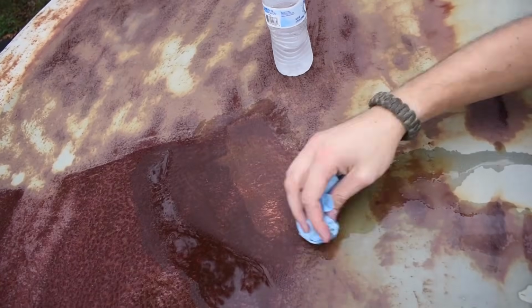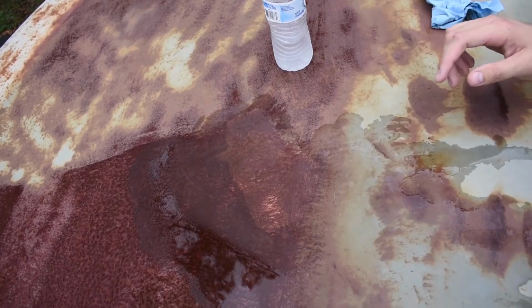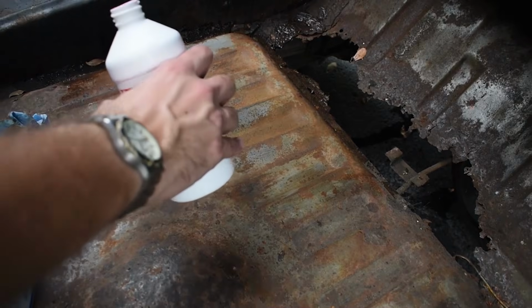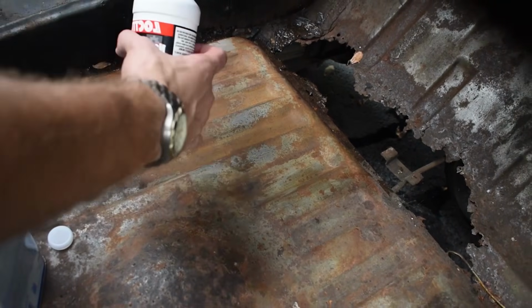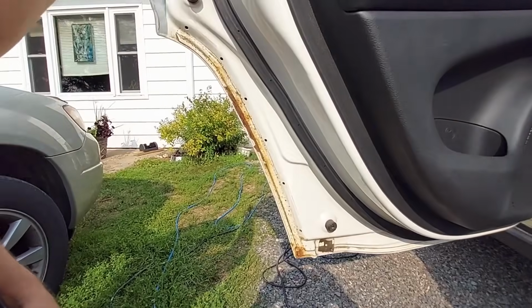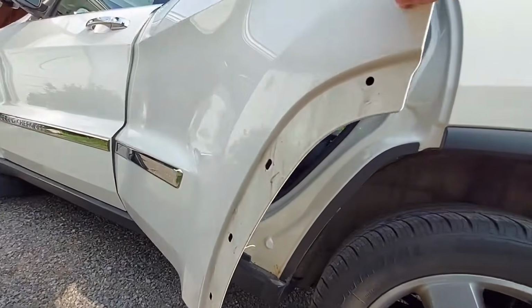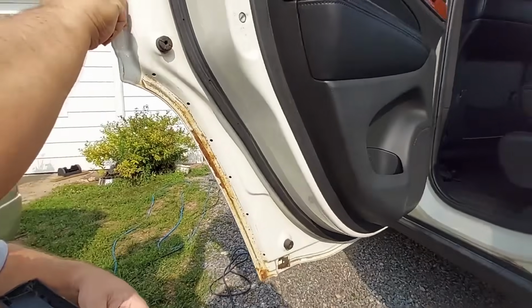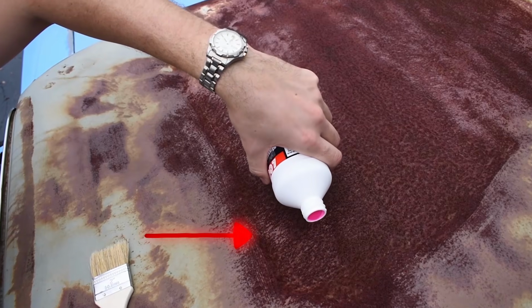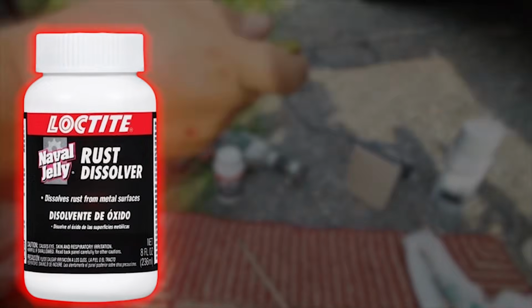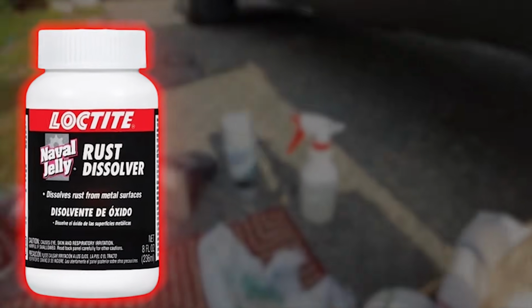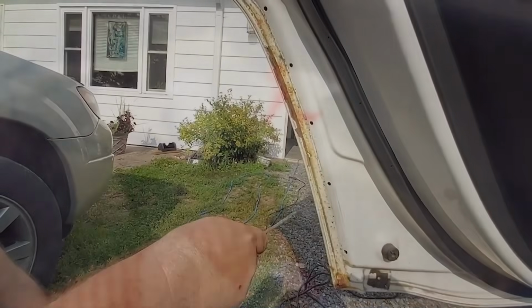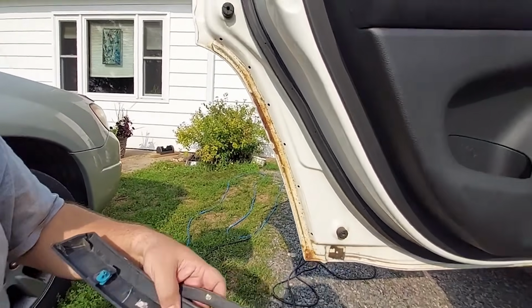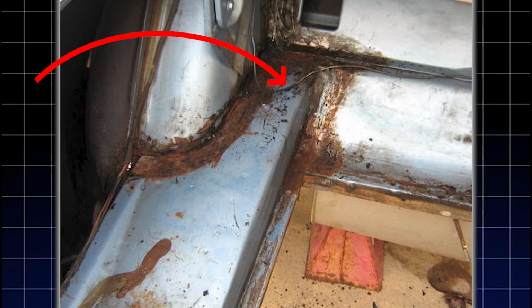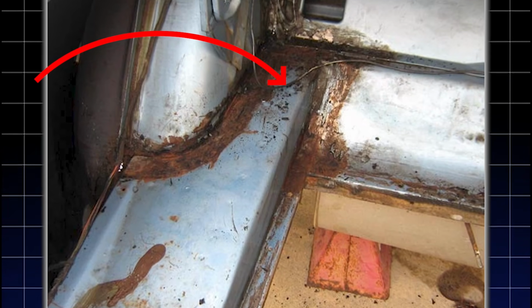On light frame rust, 20 minutes of contact time with a phosphoric acid gel produces adequate surface conversion for top coat application. On moderate frame rust with pitting, the same 20 minutes of contact time converts the surface layer, while the pit depths receive inadequate treatment time. The thick gel formula actually works against penetration into pit surfaces because the viscosity that keeps the product on vertical surfaces also prevents it from flowing into the narrow geometry of rust pits.